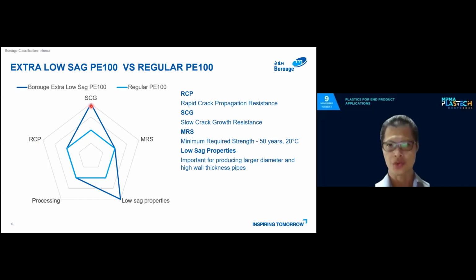SCG is slow crack growth. If the pipe has a small cut or a groove, this groove will grow through the pipe wall thickness. But this material, the extra low sag, has this feature of slow crack growth resistance. That means the crack will grow slower than the standard PE100 material. For MRS, both are PE100, so the rating is the same, so they can take the same pressure.